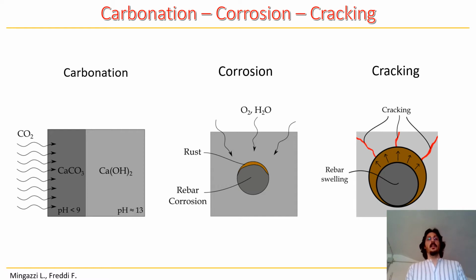This is a critical aspect, since the reduction of the pH leads to a depassivation of the steel rebars, and the corrosion process can be started by the oxygen and the water in the proximity of the reinforcement bars. And due to the corrosion process, rust deposits might form adjacent to the rebar and create a swelling phenomenon, which leads to overpressures in the surrounding concrete, which might suffer from cracking and spalling.